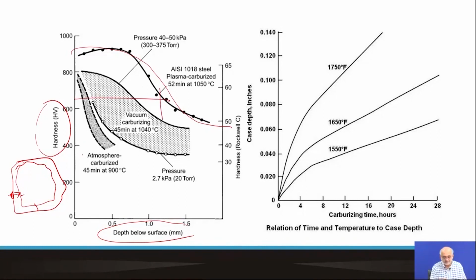This is typically in case of vacuum carburizing, but we also can have fairly good hardness maintained depending on the time-temperature combination. The case depth as a function of time will vary depending on temperature. So as the temperature goes to a higher level, the case depth is higher for the same period of time, for the same length of time.